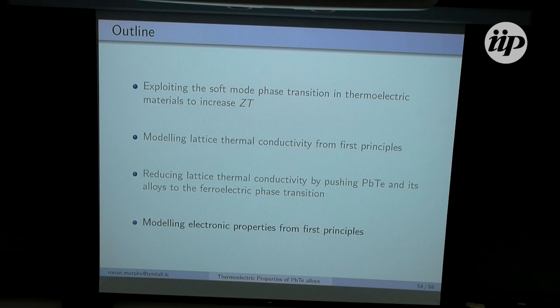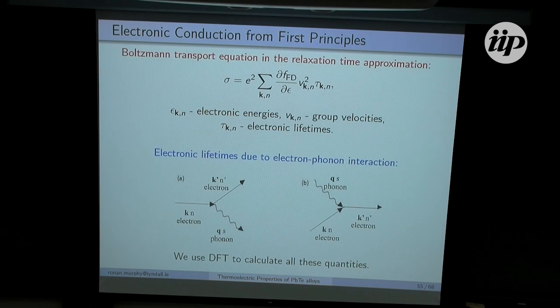Okay, so now I'll move on and talk a bit about the final part, which is modeling electronic properties from first principles. This will be a slight change of gear, and it will be fairly obvious when I'm talking about it that this is still very much a work in progress. But nevertheless, to start with, we return to the Boltzmann transport equation in the relaxation time approximation. This is the formula for the electrical conductivity, where epsilon are the electronic energies, v are the group velocities, and tau are the electronic lifetimes. Now we model these electronic lifetimes due to electron-phonon interaction, and we use DFT to calculate these quantities.